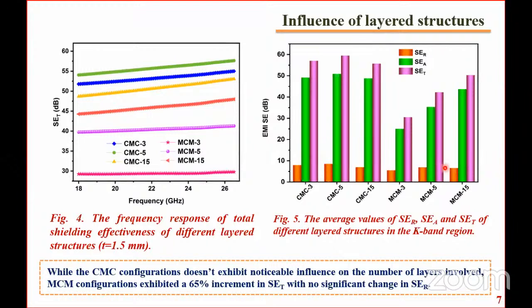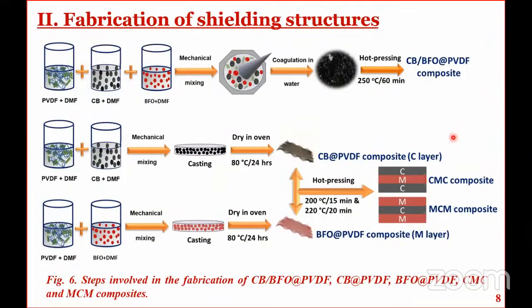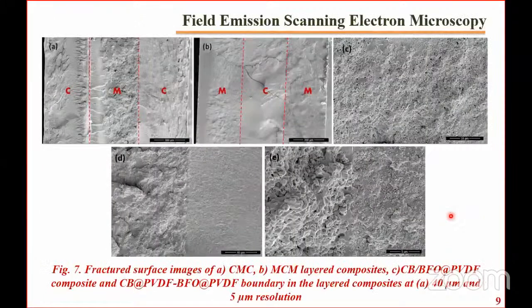There is no increase in reflection-based shielding, only the absorption-based shielding is increased, and this can be attributed to the impedance matching of the magnetic material that we have placed in the first place. In order to test our theory, we fabricated all the shielding structures using the coagulation and hot pressing method, and the casting and hot pressing method. This is the field emission scanning electron microscopy, and from this we can see that there is no diffusion between the magnetic and conducting layers in any of the composites, CMC and MCM. So the layers are intact even after hot pressing.